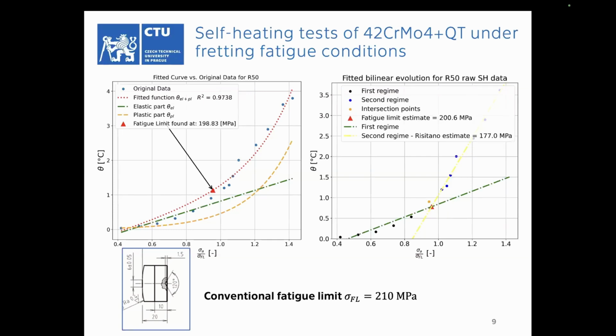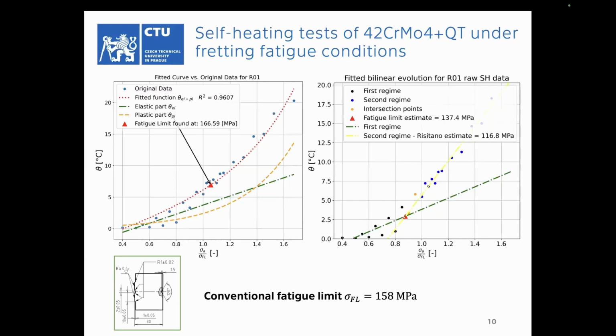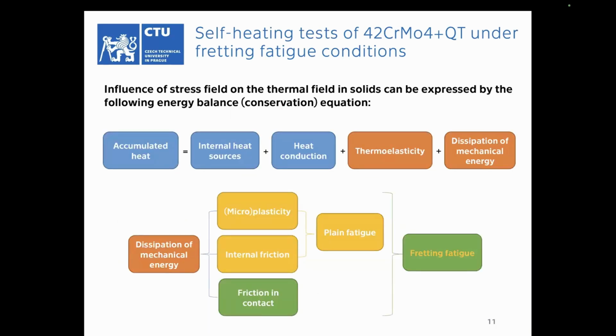In the case of these single surface pads. If we take a look at the data from the bridge pads, the difference is almost the same for our approach, and here we have a slightly bigger difference, around 12%. So we might conclude from this that the estimate of fatigue limit is not that bad, but one might argue that we are sort of breaking the original bounds of application of the self-heating method, which was, as I said, originally intended for plain fatigue tests.